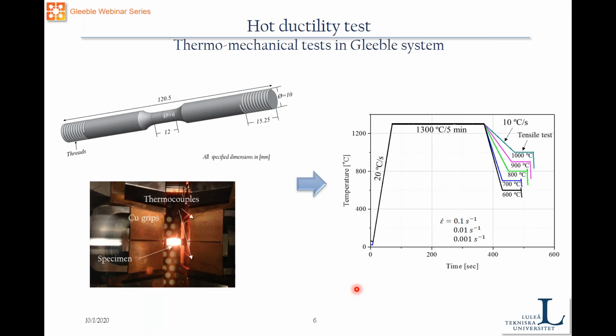The thermal cycles look like this. We were controlling the heating of the specimens at 20 degrees per second up to austenitization at 1300 degrees. We applied a holding time of 5 minutes. The idea was to ensure that the austenite was homogeneous, and also to make all the precipitates dissolve, so they cannot affect the final results during the test.